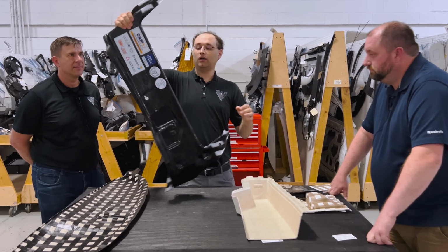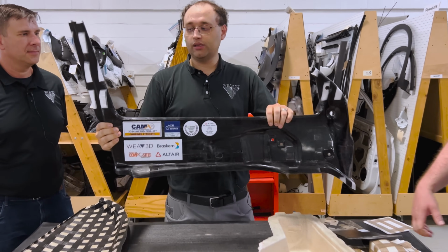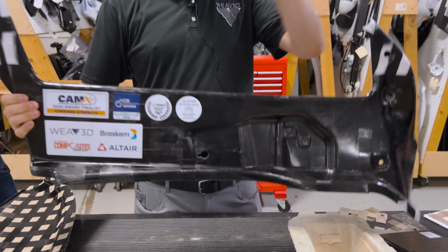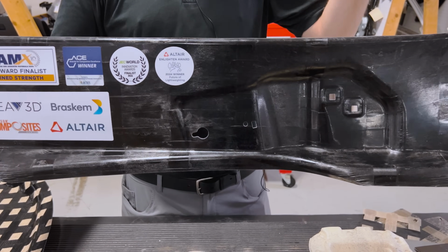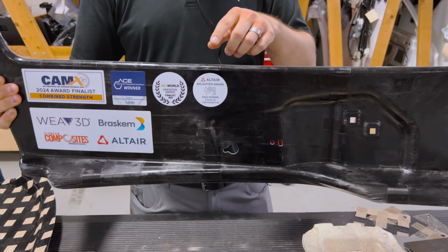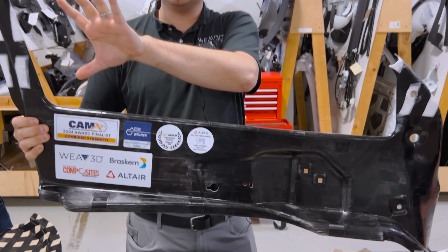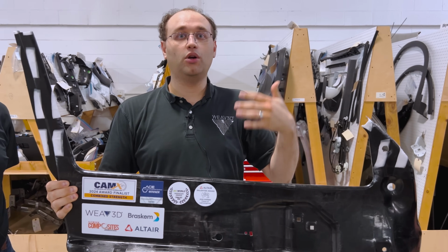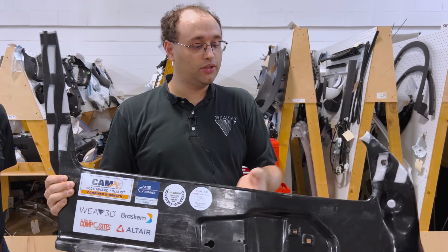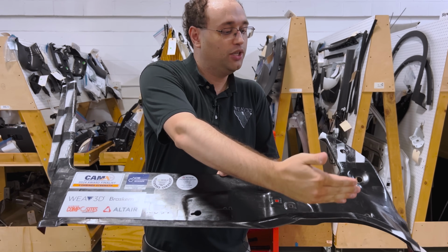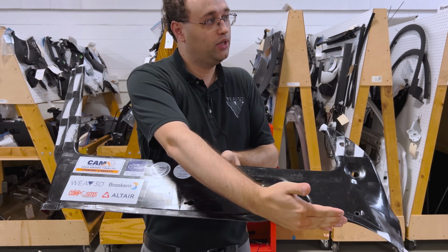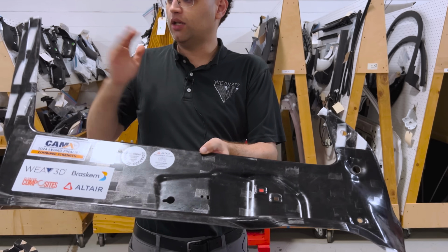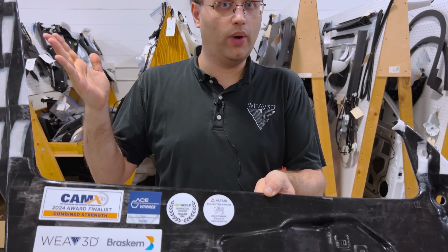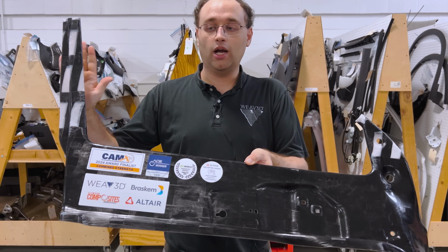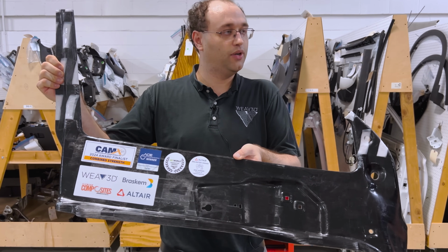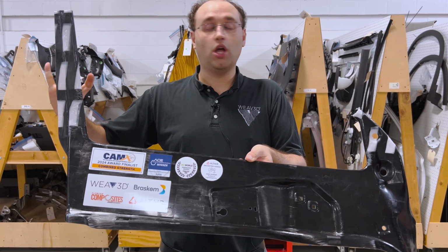And I didn't point it out earlier, but this particular part is thermocompression formed, so it starts off as a big rectangular sheet that you heat up, stamp, and then trim. In the area up here where the window is, you're going to be trimming all that material off, so you don't want to pay for it. In this design, we used a much higher density of tape from about here to here, but up in the A and B pillars, where you're going to trim this out anyway, and the part gets glued onto another structure that provides its stiffness in this area, we could go much lower density on the lattice.